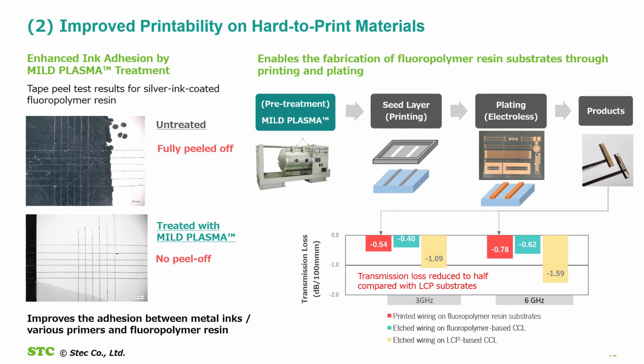The second application is printed electronics. Whereas fluoropolymer materials are attractive, they are also difficult to print on. Mild plasma improves the adhesion between metal inks or primers and fluoropolymer resin. As shown in the tape peel test, untreated samples peel off completely, while mild plasma-treated samples show no peel-off. I would also like to highlight that transmission loss of fluoropolymer resin substrates treated with mild plasma can be reduced to half compared with LCP substrates. This means customers can consider new process routes such as printing and plating to fabricate fluoropolymer resin substrates.